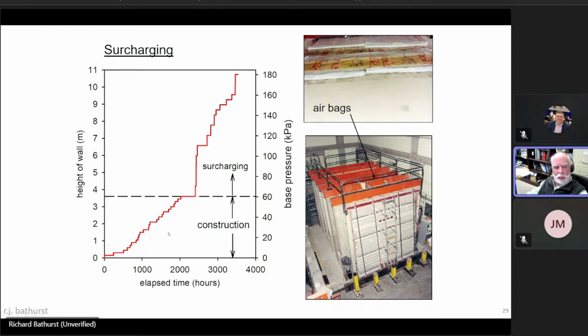So the plot that you see here traces the construction of the wall based on height and foundation pressure up to the end of construction. And then after construction, we kept surcharging this wall in an organized way until finally there was a failure. And it's interesting, you can see that the surcharge pressure was about 3 times the maximum pressure at the base of the wall at the end of construction. So you can see there's a lot of inherent load capacity in these structures.